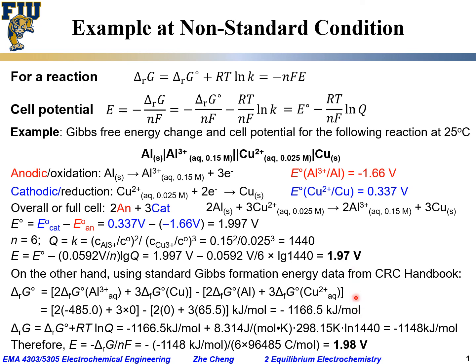Okay, so you see we can get almost the same cell potential either directly using the standard electrode potential series and correcting with the Nernst potential for the concentration effect, or we can first calculate the standard Gibbs free energy change for the reaction and correct using the reaction quotient term for the Gibbs free energy, and then calculate the cell potential, and the result should be very, very close. Okay?